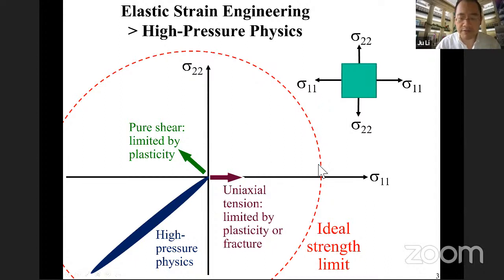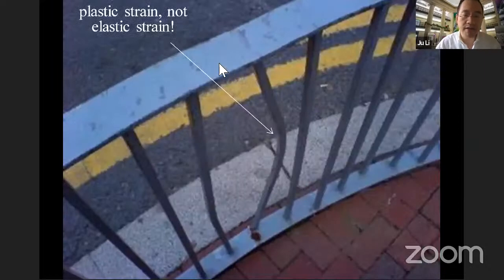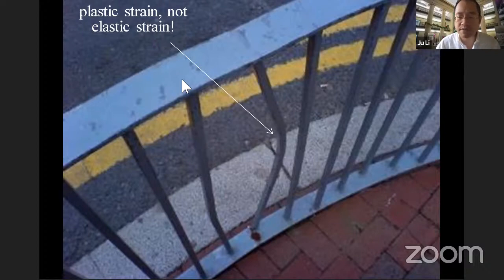And you'll be very far away from the so-called ideal strength limit. This is what a perfect crystal lattice can sustain at zero temperature without any defect. I just want to remind everyone that we know metals can easily deform 30, 50%. But in this situation, this is almost all plastic strain. The elastic strain is typically less than 0.1%.